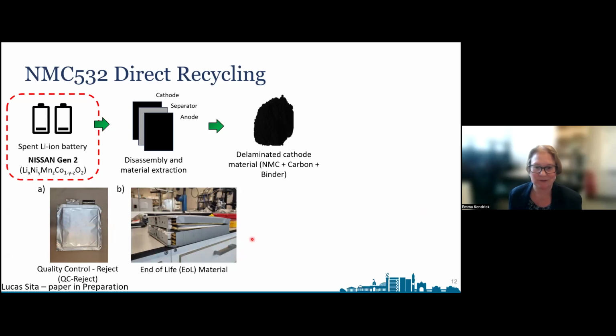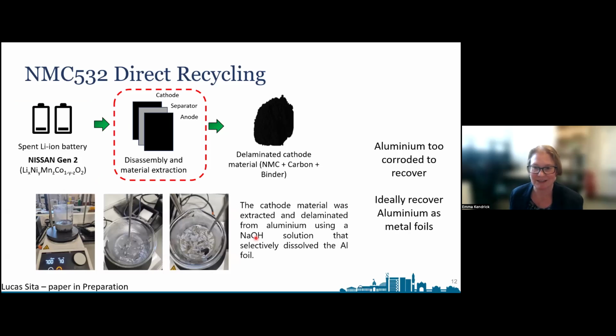Interestingly, in this case, the quality control rejects were not filled, they were open, and they're a few years old, which meant that the delamination was rather difficult and everything had kind of stuck together. The aluminium had basically corroded within the cell, which meant the only way that we could recover that, rather than using an ultrasound method, was actually to dissolve out the aluminium, which is obviously not really wanted, because ideally we recover the aluminium as metal so that we can recycle that directly again, rather than having to dissolve it out and then using enormous amounts of energy to remanufacture aluminium.